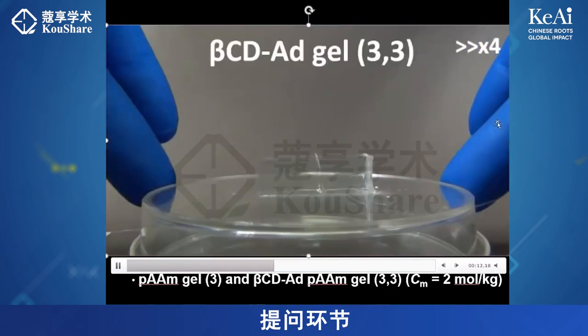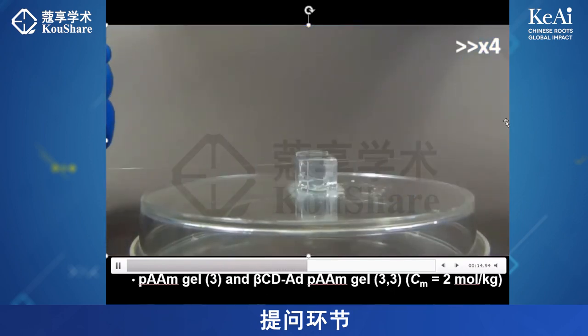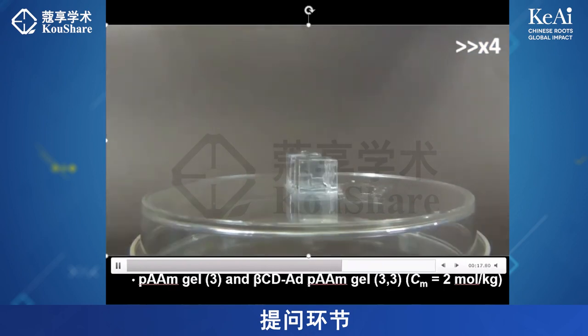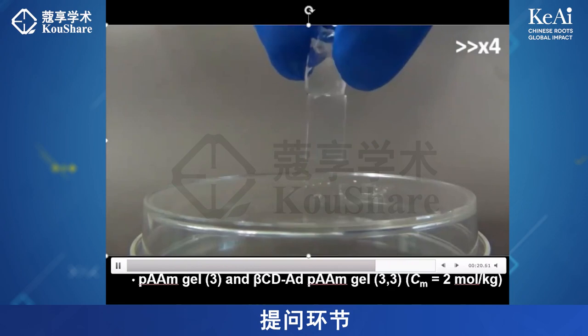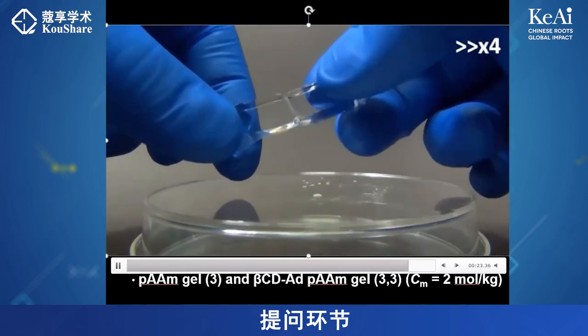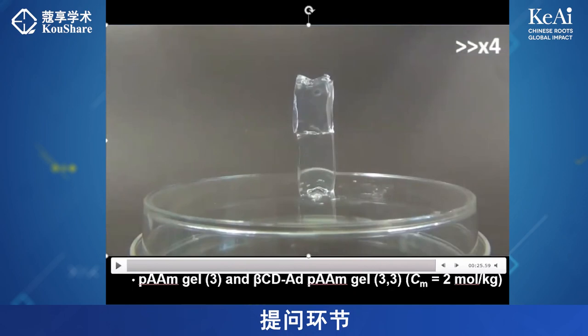This is the usual covalent gel. This is a supramolecular gel. When you cut the gel with thin strings, the cut surfaces have already adhered, so you cannot cut the gels with thin strings. When damage occurs, the damaged part is mended, cured, healed at the same time. So this is quicker than our body, I think so.